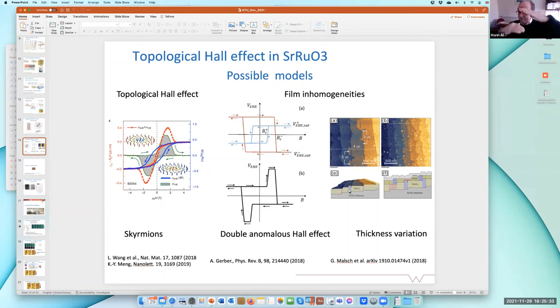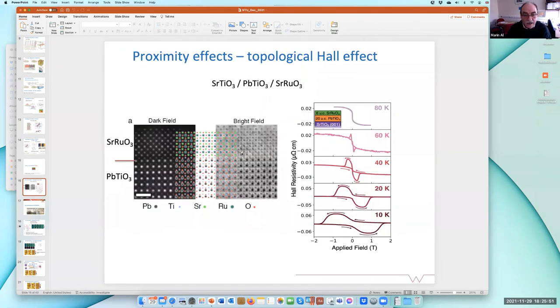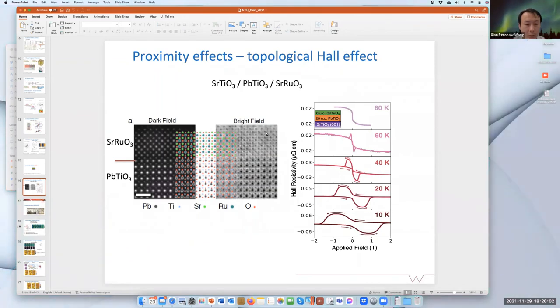But if you have layers, it's completely different because you have a parallel flow of two rivers of electrons, each flow with its own interaction. And as we have seen here, half of this thin film is non-centrosymmetric. Half of the thin film is centrosymmetric. So it might be that one has one anomalous Hall effect, the other one has another one. Whether this is related to the magnetic structure we have seen, I cannot answer this question. I see. Yeah, it's pretty complicated.